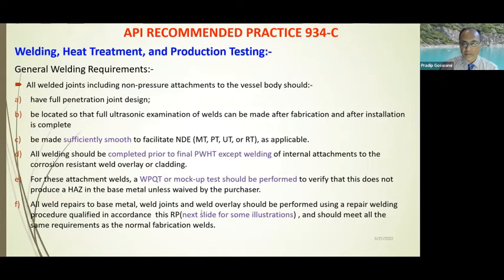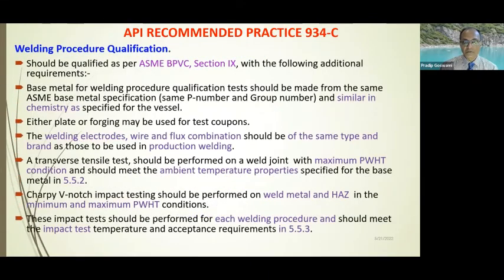And all weld repairs shall be done using a repair welding procedure qualified in accordance with this RP, and it should meet the same requirement as the normal fabrication welds. That means any welding repair you do has to be qualified prior to application on these equipments. And welding procedure qualification, as I mentioned earlier for 934 in course of 934A, should be qualified as per ASME Section 9, with the following additional requirements.